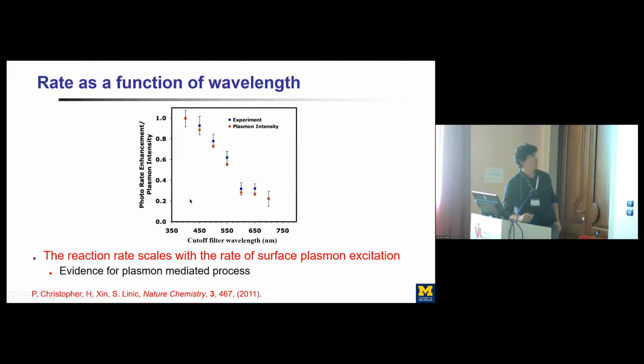The first experiment is really simple. Here we're trying to understand whether these rates are higher under the condition of resonance, when you're actually exciting the localized surface plasmon resonance. We use optical filters to tune the photons that are hitting our sample, our reactor. And what we see is that when we excite this localized surface plasmon resonance, we actually see chemical reaction taking place. And this is really not surprising. What it's telling you is that the more light you extinct through this localized surface plasmon resonance process, the higher reaction rate you're going to have. The more energy used by the system, the higher reaction rate you're going to have. So this is really not that surprising.